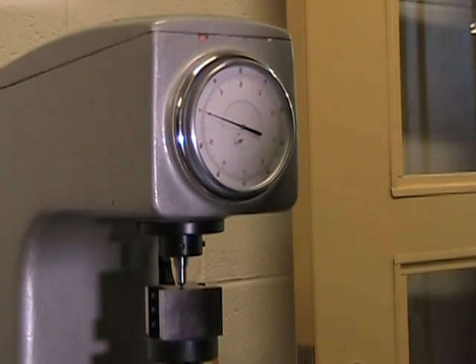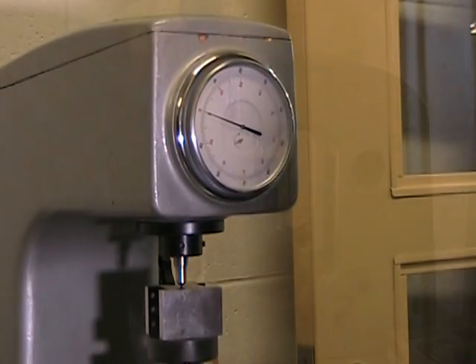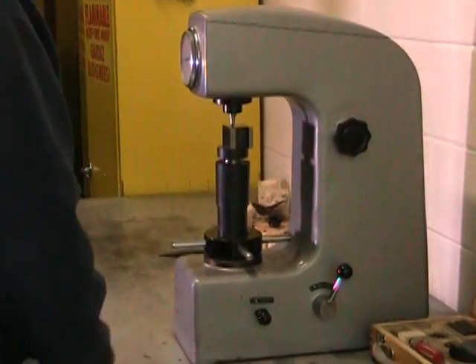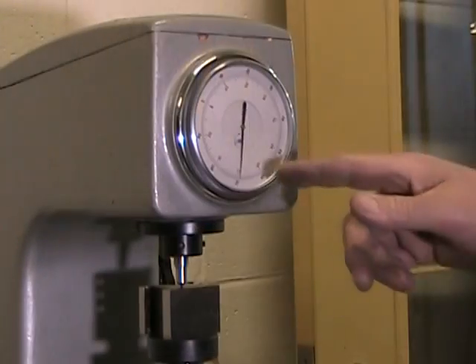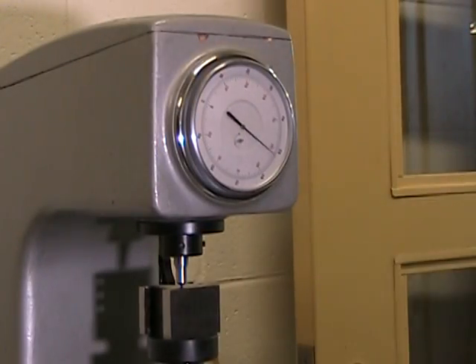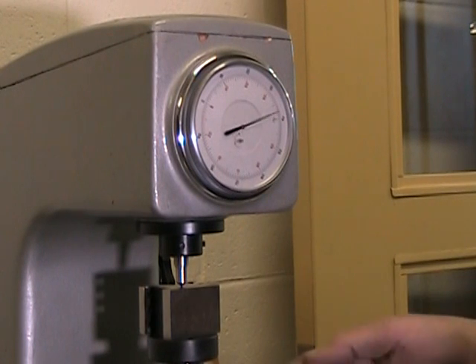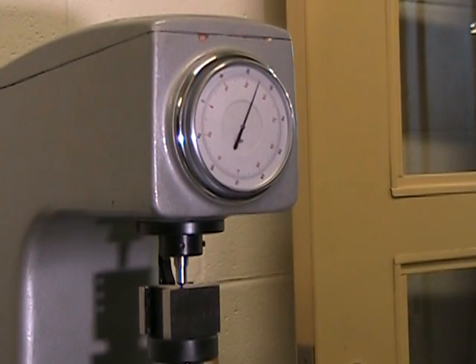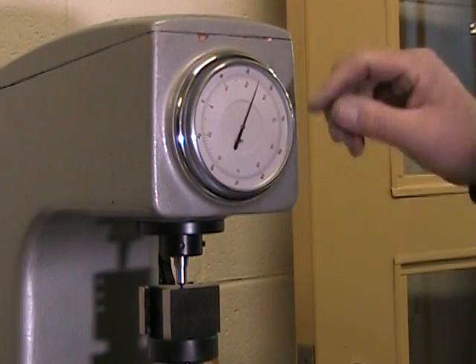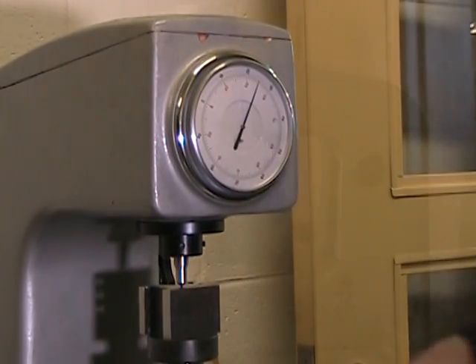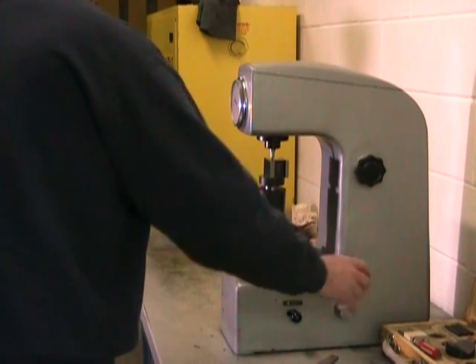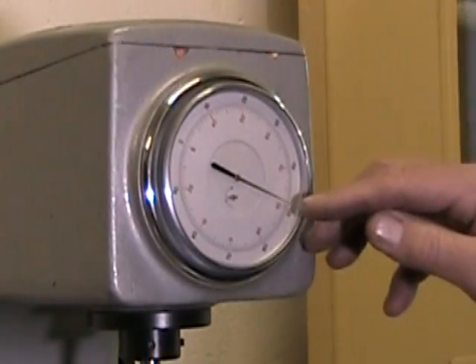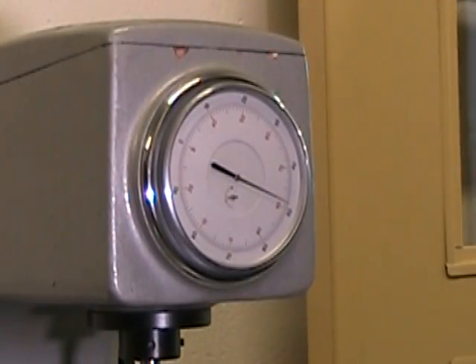We're now ready to activate the machine, and to do that we're going to use the load engagement lever. We can see here that the dial is still moving, and that means that we're still penetrating the part. Once it stops, there we go, that's not the proper reading. We have to return to our preload. So let's go back to our preload, and now we can read the scale, and we see that we have about 48 Rockwell. Pretty well what I expected.